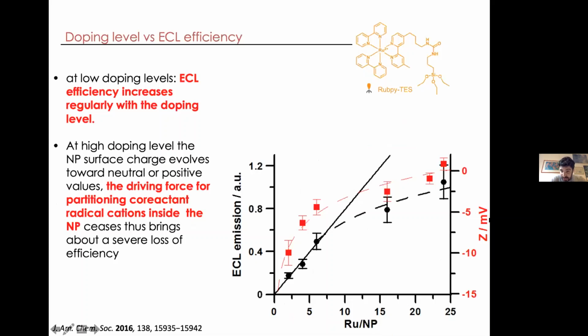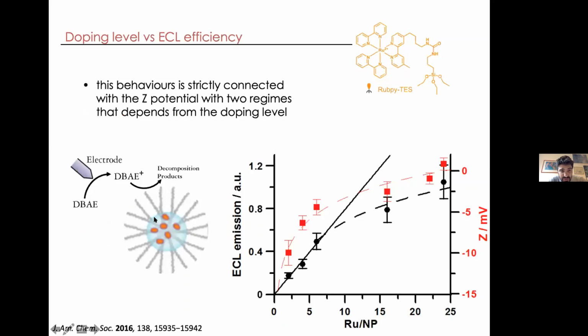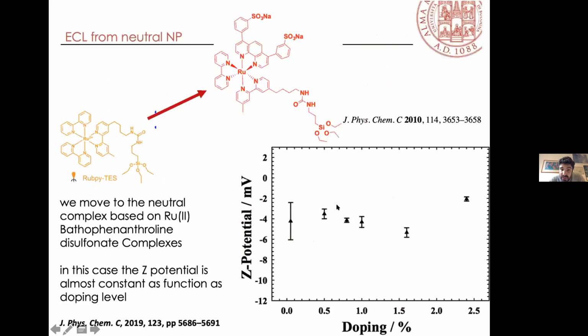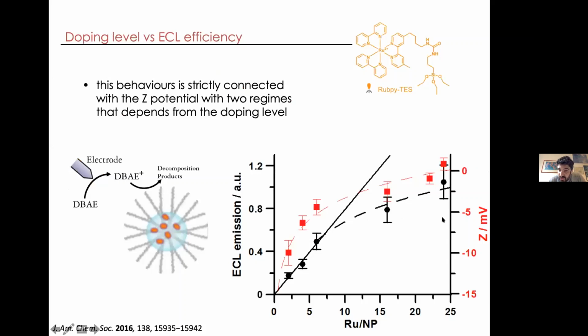We measure, for example, Z potential, that I think is quite interesting. And here I'm reporting the red dots, which are the Z potential. You see that Z potential becomes almost positive at such doping level. So it means there is some charge involved. Nanoparticles become positively charged, and there are some electrostatic effects that are involved in the ECL generation. In fact, we are using this with the co-reactant mechanism, so the TPA radical cation cannot penetrate into the shell of the nanoparticle where the nanoparticles are positively charged. Okay, but why do we go to such a positive Z potential?